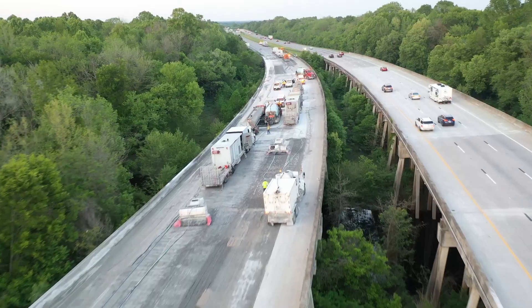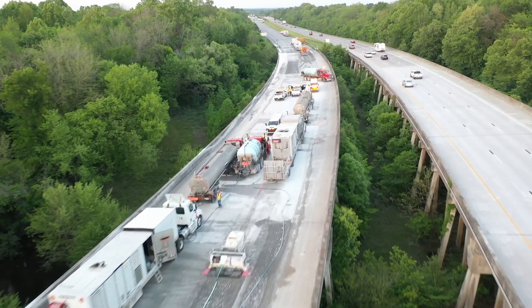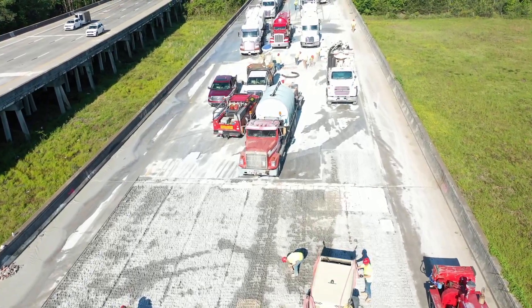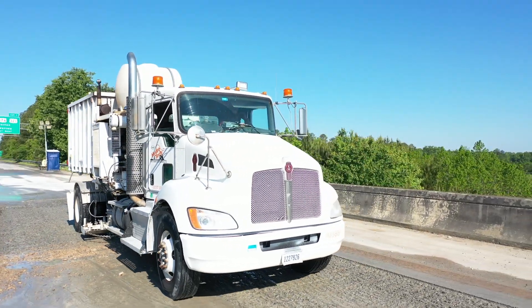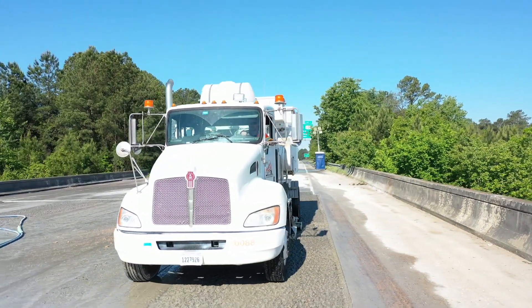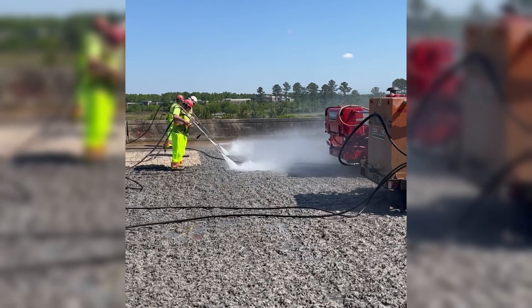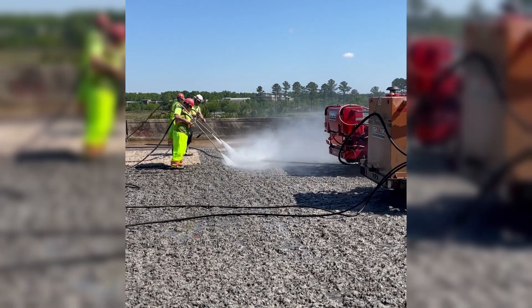The third step involved the cleanup of hydro demolition debris and preparation of the existing bridge deck surfaces. Areas inaccessible to the hydro demolition equipment were jackhammered lightly. The concrete finish machine was set up and run to achieve the proper profiles. The deck was then power washed at 7,500 psi minimum, left in a saturated surface dry condition, and covered with plastic, ensuring a clean and bondable surface for the new overlay.